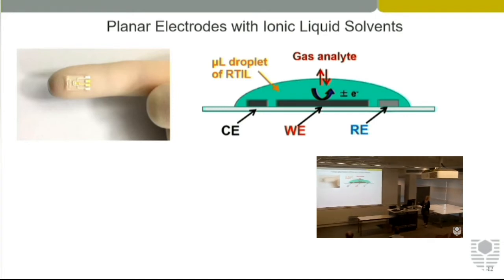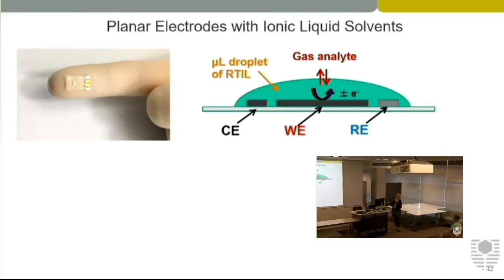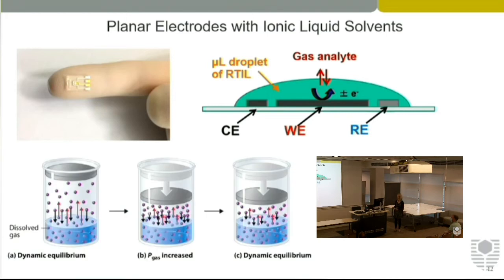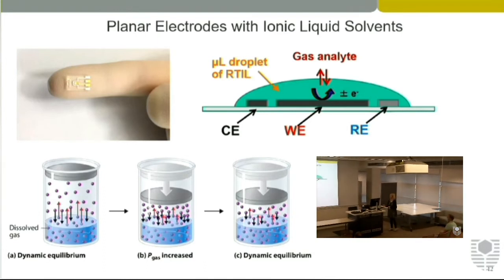In our experiments, we then have a gas flowing continuously over the ionic liquid. We have a partitioning step where the gas dissolves in the ionic liquid. And then once we have equilibration, we can apply a potential to oxidize or reduce that gas. If you go back to the undergraduate thermodynamic theories, if you have gas in the gas phase and gas in the liquid phase, you'll be at equilibrium. If you increase the pressure of the gas or increase the concentration, then you'll force more of your gas molecules into the liquid phase until you're in equilibrium. So you need to be in equilibrium, so that you're actually measuring the concentration of the gas in the liquid phase, but that's related to the concentration in the gas phase.